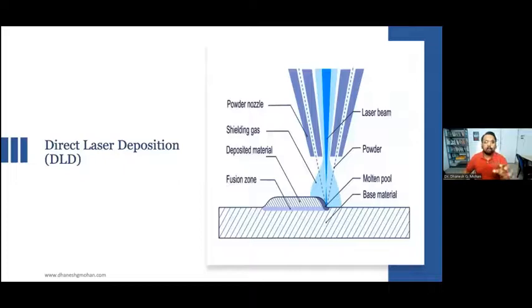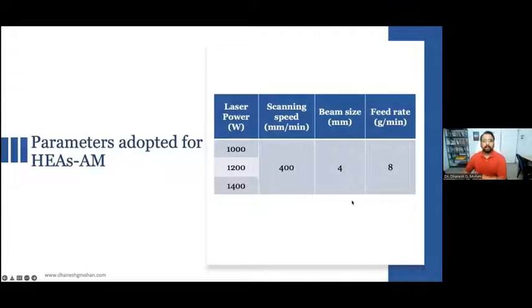Let us see what method we adopted for our high-entropy alloy additive manufacturing. This is the direct laser deposition method. You can see in this image what direct laser deposition is: there is a focused laser over here, and from this nozzle the powder is sprayed, shielded by argon gas. While the powder is coming out through the nozzle, it's melted by the laser beam, and each layer is formed by this molten base metal. Clear?